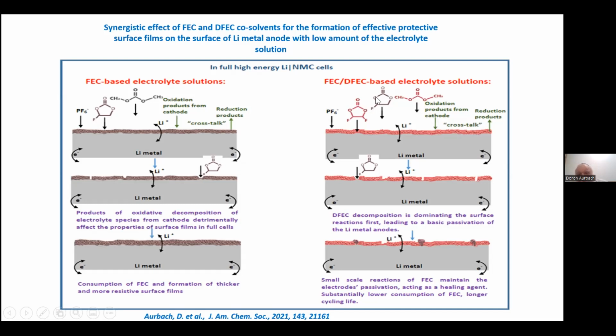The FEC reacts as a healer. So whenever there is any weakness in the surface film, FEC is reacting, and we were able to show results by spectroscopy, XPS, and FTIR. We did these stepwise studies, and came up with the understanding of what's going on. So we have this mechanism of healing. First of all, DFEC is reacting, but then we have FEC that heals the cracks whenever there is instability in the surface film. We have reactive FEC that repairs the material.